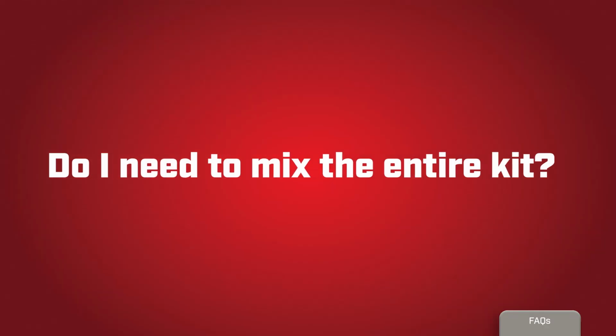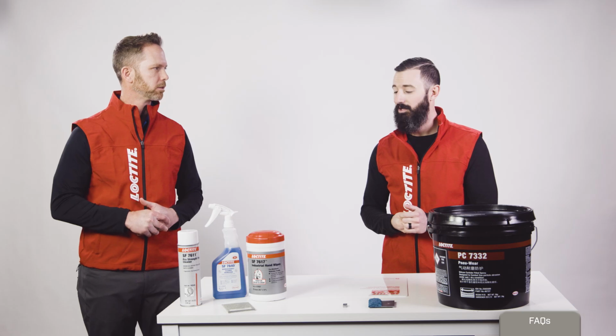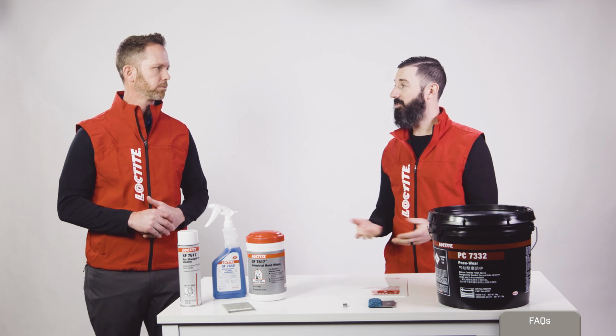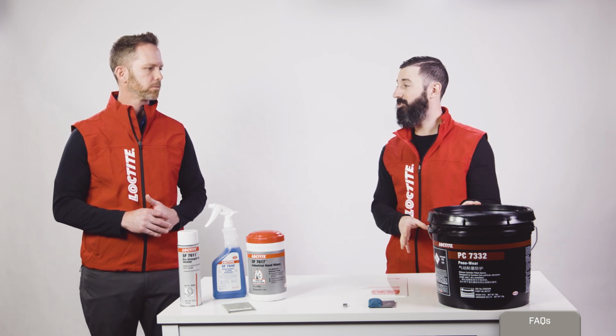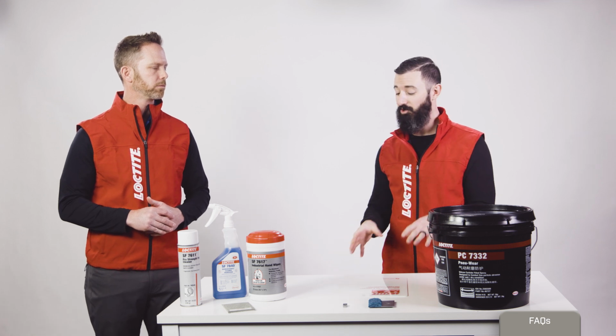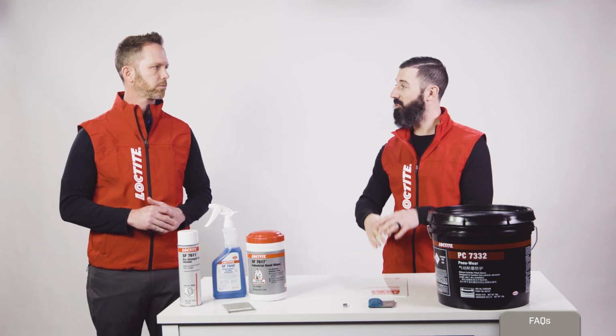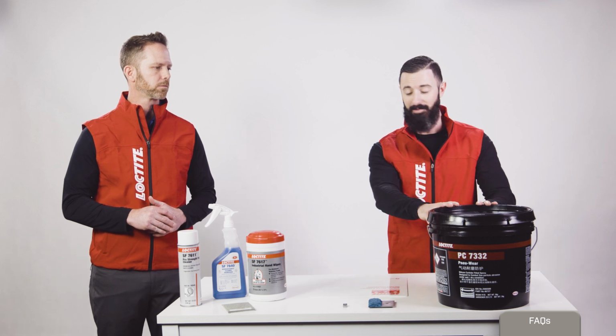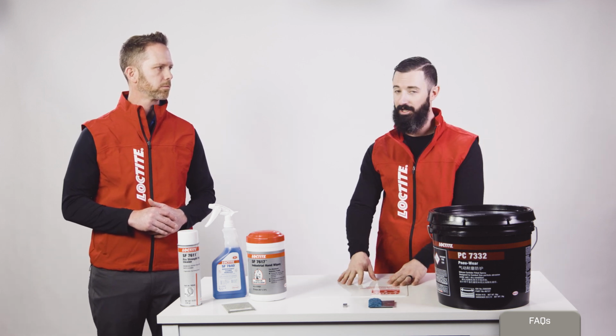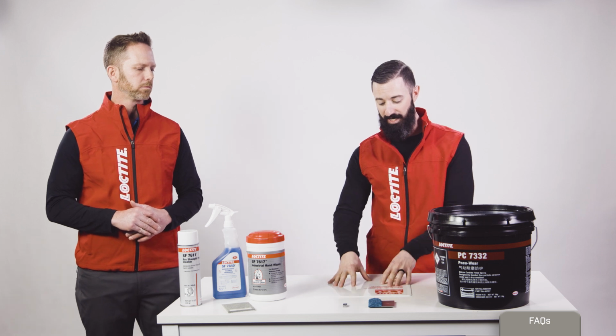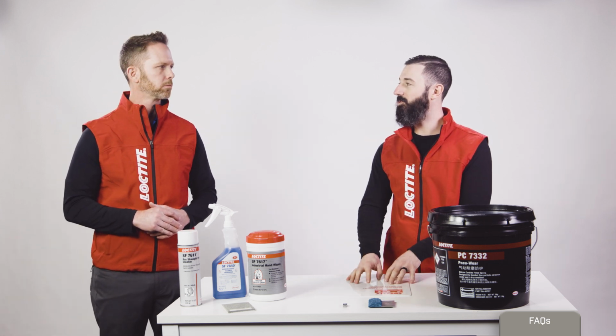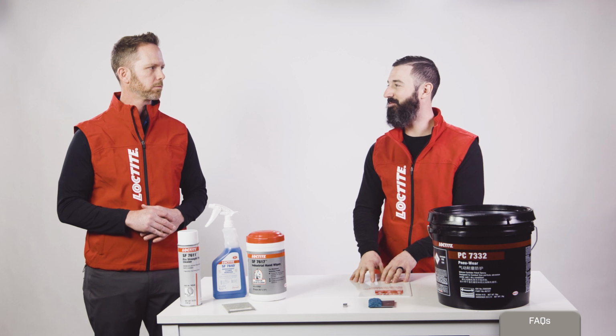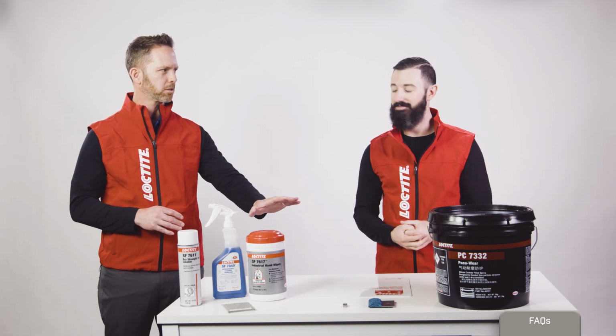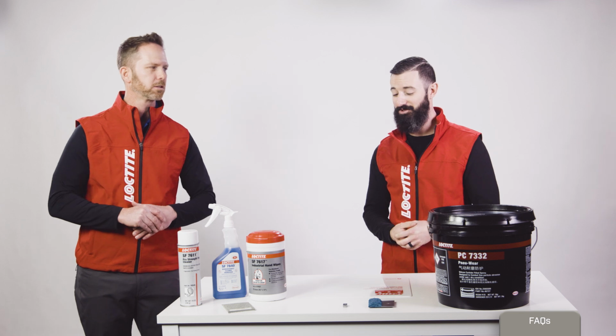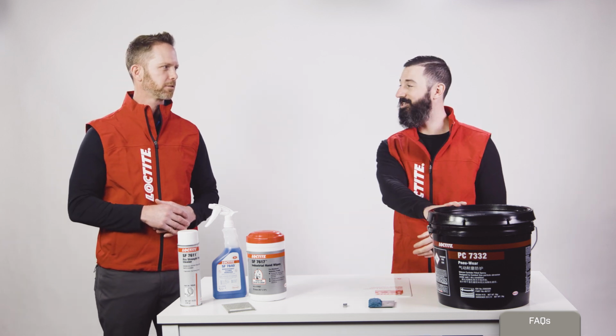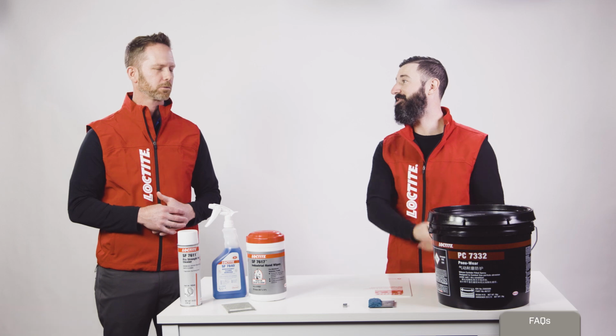And do I need to mix the entire kit, or can I mix it in smaller batches? The ideal scenario is the whole kit. They're pre-measured, pre-weighed out in the proper mix ratio, but you don't absolutely have to do that. You can pull out part of it, as we talked about before, using just small sections of it. You can cap it, use the rest later, use only what you need to use. The method for doing this is using the mix mat where you're doing a figure 8 pattern. Just make sure that you're using the information on the technical data sheet for the right mix ratio. And don't contaminate your equipment with the different products. Absolutely. If you're touching your hardener, don't then go touch your resin and vice versa, because then you may have issues inside the pail. Right.